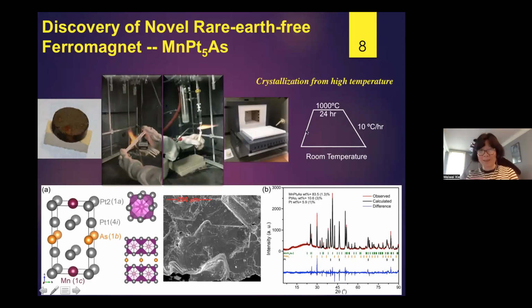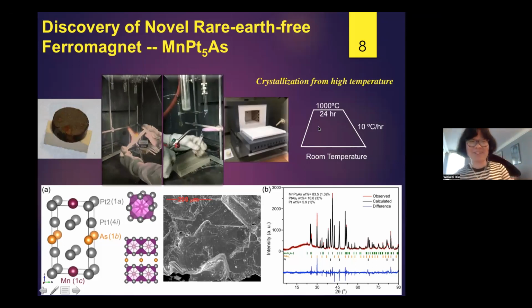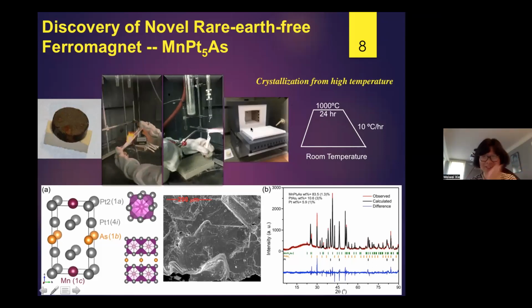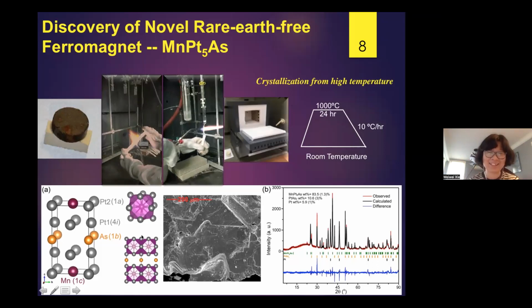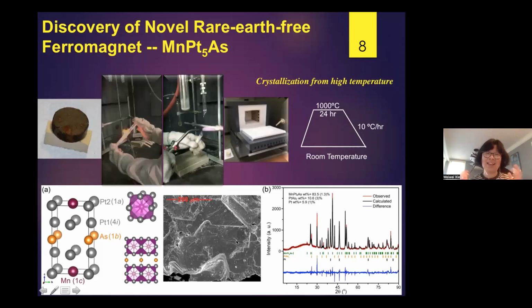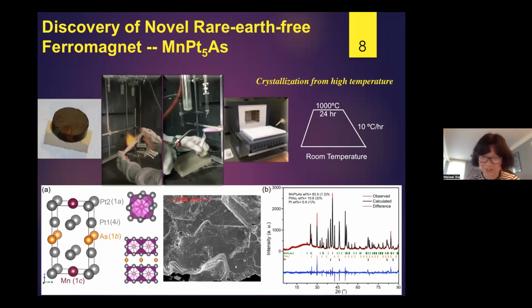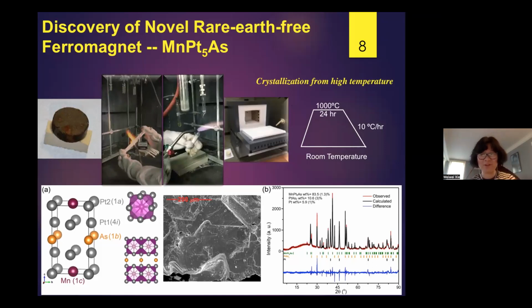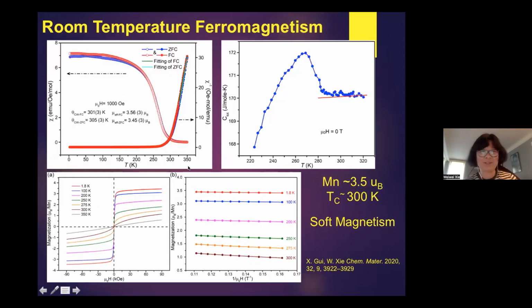This is the chemistry lab, how to make the experiment. So we seal the tube, we put it into the furnace and heat it. And then this is the compound we got. And we do the X-ray to study the structures and do the refinement to confirm the phase. And then we measure the properties.